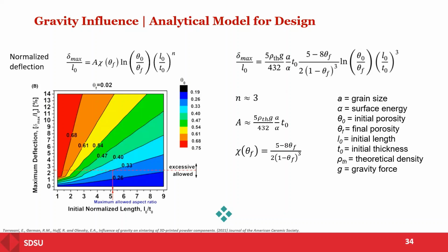analyzing our results and getting a more simplified relationship between porosity and all the parameters like initial thickness and initial length, we created this sort of map. This was for the ceramic material, where on the x-axis we have what we call the normalized length, that is the length divided by the thickness, and here the deflection, so how much that beam has been deflected. This kind of map lets you, if you want minimum distortion, decide where it's allowable or where it becomes too excessive based on the initial geometry of your part. And this was the last slide of